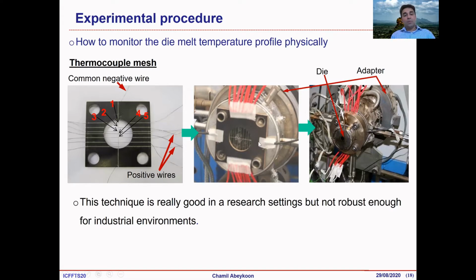I'm not going to get into details about this technique. This is how this thermocouple mesh technique measured the melt temperature profile across the melt flow. But this is really fragile. You can see tiny wires here, so they can be easily broken, and it also disturbs the melt flow and adds some shear heating effect. Therefore, this is not viable in industry.